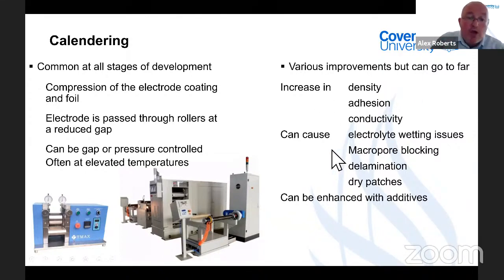You've got to be careful though. If you go too far, you can cause problems with wetting. You can't get your electrolyte to go into your final cell. Sort of counterintuitively, if you compress too hard, you can end up delaminating. The material will bounce back and come apart. You come up with things like dry patches occurring in your electrode when it comes to the electrolyte wetting.